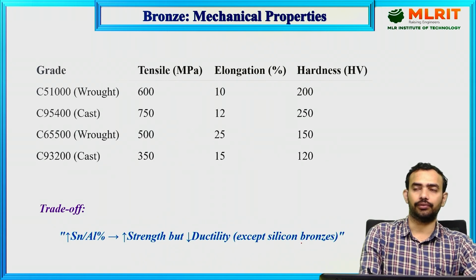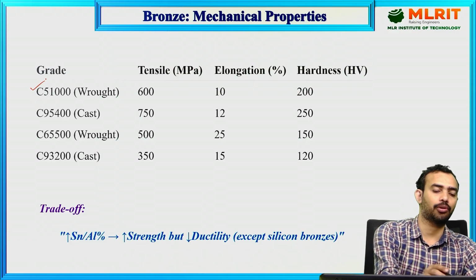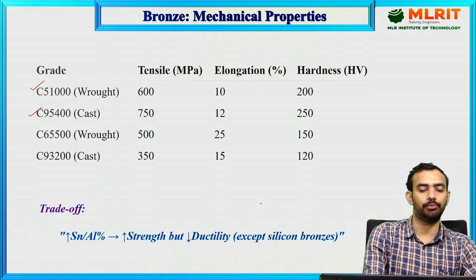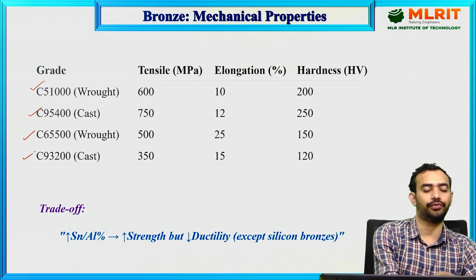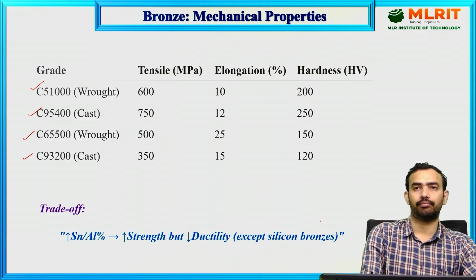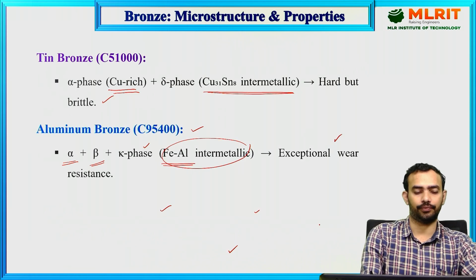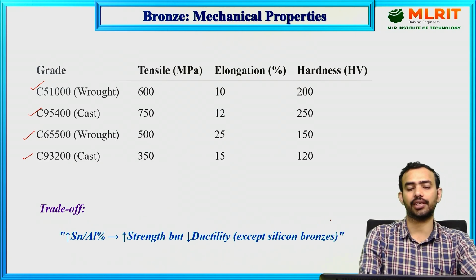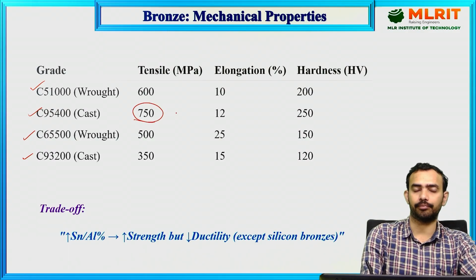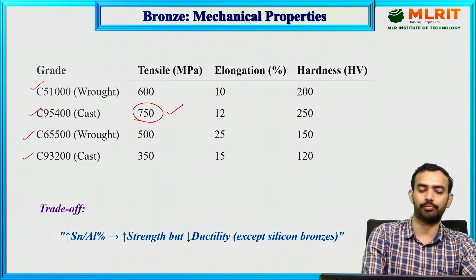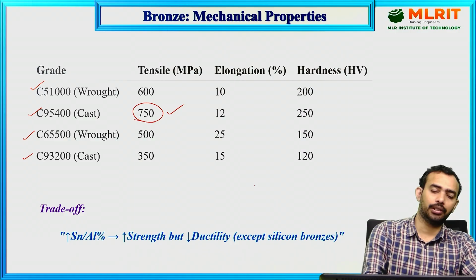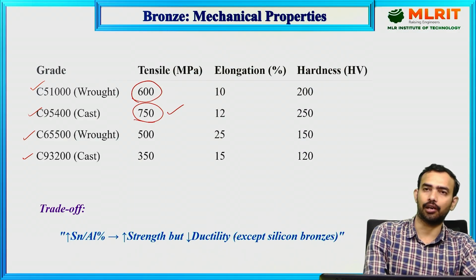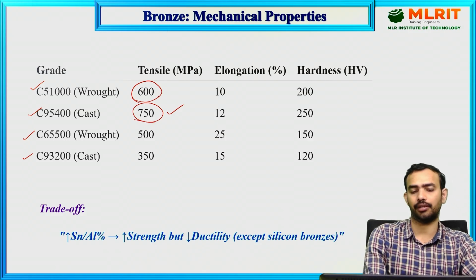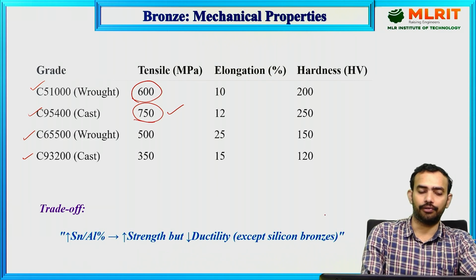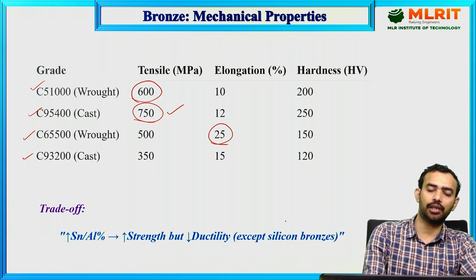Okay. If you see the mechanical properties of all these alloys, wrought alloys and cast alloys, this is a phosphorus bronze or the tin bronze, we can say. Then we have aluminum, then we have silicon, then here is our leaded bronze. If you see its tensile property, with aluminum and the presence of iron, its tensile strength is shooting up significantly, to 750 MPa. It's a good number. In general, with the addition of tin alone, it can have tensile strength up to 600, a pretty good number. And if you look at the elongation or the ductility of the material, silicon is giving very good ductility.